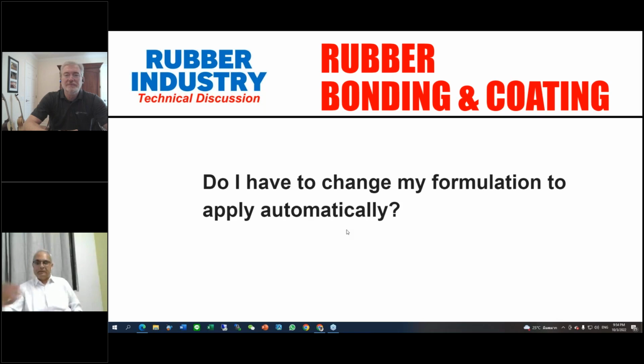Very true. By so much addition of solvent, I'm changing the percentage in the system, and that is creating a problem. And this problem may not be understood unless the failure is analyzed, many times through root cause analysis, right? Correct. As we showed on the solvent continuum, there is a recommended solvent level and viscosity that, for instance, Parker Lord suggests. This formulation is very important, and that should always be kept in mind by the users.